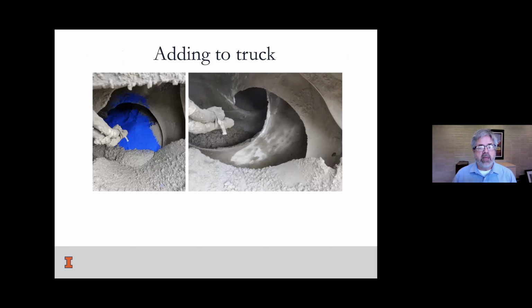Here's a picture of one of the SAPs. That's not colorized. That's the way the SAP was, a nice blue color. And so we've added it into the back of a truck. And in fact, it just blended. One thing we notice is that it sometimes might get a little bit agglomerated on the surface of the blades, but I think there may be even some ways to be clever about entering it so that it doesn't even have that much problem with the blades.